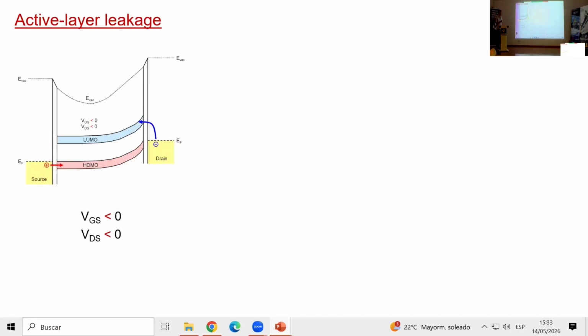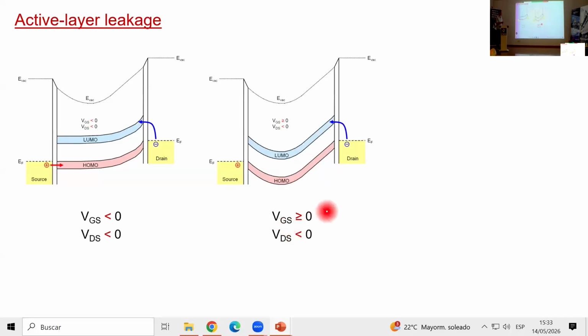So now I'm going to turn the transistor off. So to do that, I choose the gate source voltage to be positive, or at least greater than 0. So now I establish an energy barrier here, and that blocks the flow of holes from the source contact into the highest occupied molecular orbital. So I'm effectively blocking the flow of holes to turn the transistor off. But at the same time, I'm now making the barrier here that is blocking the flow of electrons from the drain into the LUMO narrower. Right? You see this, right? It's a triangle now. Here it was relatively wide. Now it's relatively narrow. And so I'm going to get undesirable injection of electrons from the drain into the LUMO. And that will be a contributor to off-state drain current. This is one of the major enemies of making a good thin film transistor.